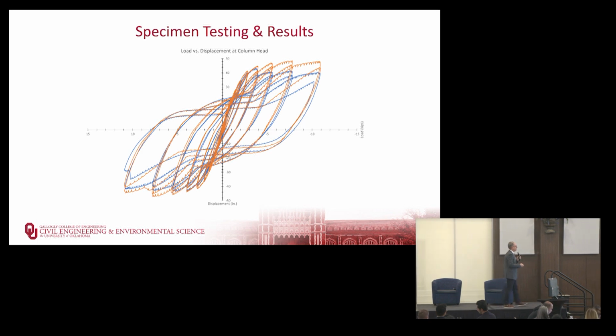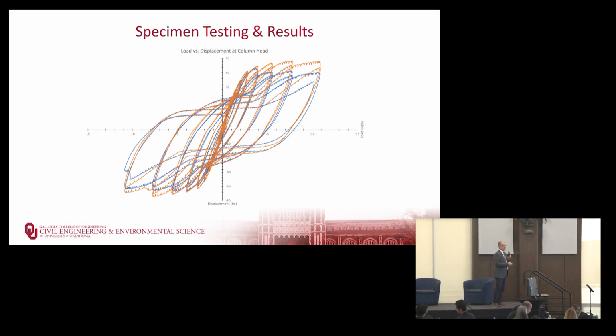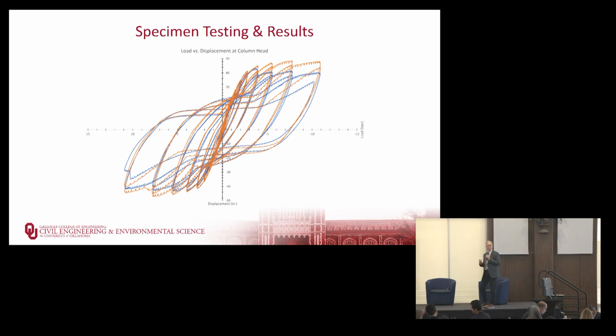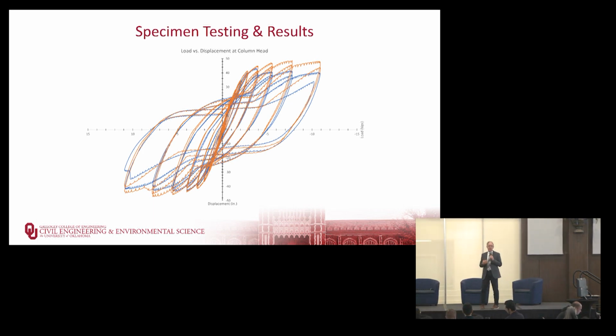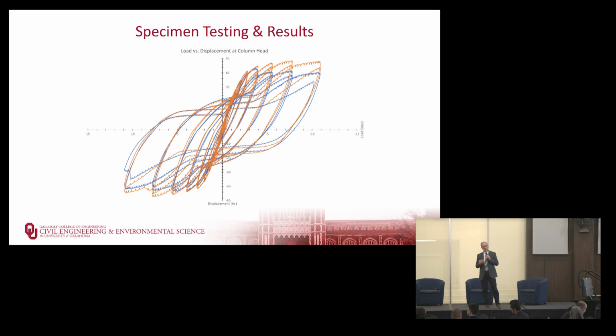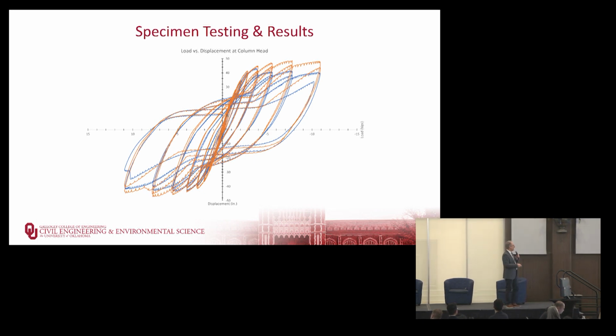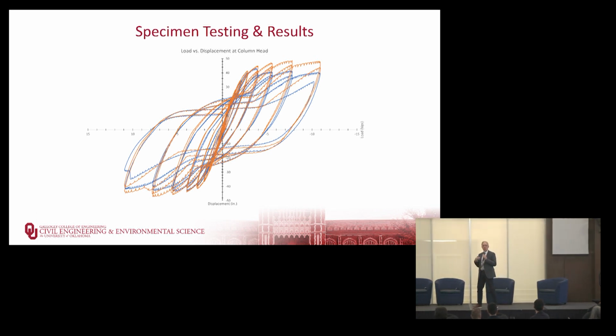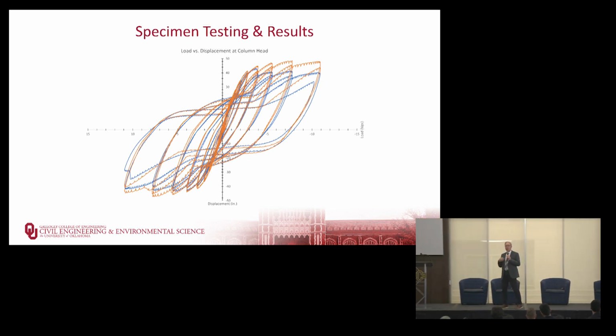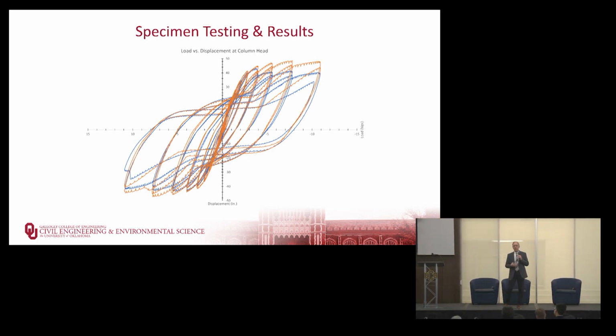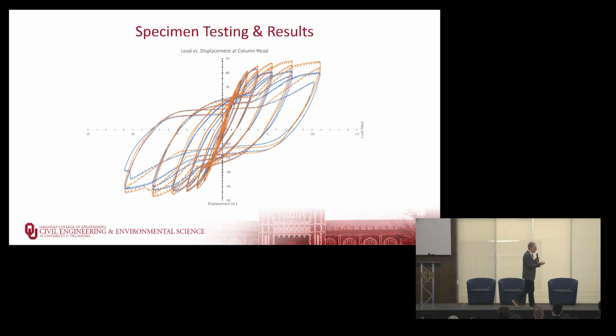And then here's a comparison of the two. It's about a 17% difference. And that's mostly because of the extra confinement that the UHPC provides. Not necessarily because of its compressive strength, but because of the small steel fibers that we put in the UHPC. And again, the important thing when we talk about durability, resilience, ductility, we all know that inside that hysteresis loop, there's energy being absorbed. That's why you want a nice, ductile response during an earthquake or a seismic event or an impact. Anything that puts a dynamic load on your columns, the fact that they can absorb energy makes them more resilient. So these are behaving very, very well.